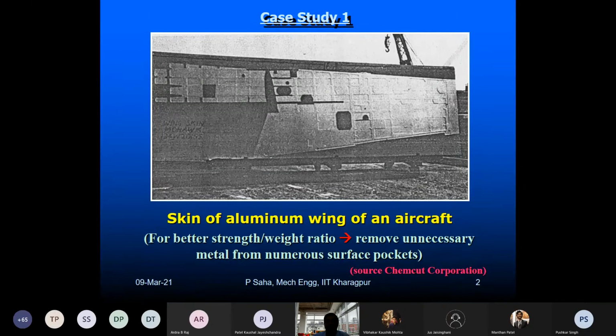Because if you remove it by, say, some kind of milling operation or subtractive machining operation, the interaction of the cutting tool with the alloy is going to induce some kind of residual stress, machining stresses, because of the cutting force. Once you have this residual stress, the fatigue life of the product becomes uncertain. And for aerospace, which flies, obviously you cannot play with the life of the component. Fatigue life should be pretty high. After repetitive flying, it should perform as it is. That should not be a failure point. So obviously machining is ruled out in this case.